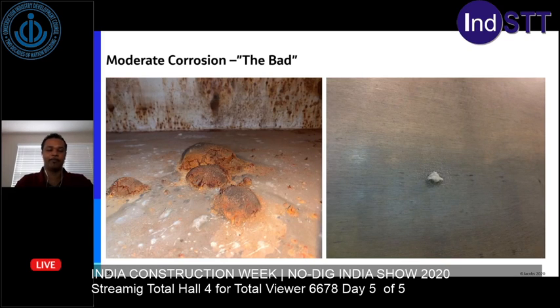And now we have a couple photos of moderate corrosion. This is considered the bad. The photo on the left has some corrosion nodules that have formed on the carbon steel tank floor. And you can also see that there are some pits starting to form on the shell of the same tank. Now on the right side, you will see a more exotic material with a feature that's similar to the nodules on the other side, but this feature has crystallized and it has allowed the product to be maintained within the structure. So that additional time that this feature allows gives you time to go in and consider adding a liner to this particular material application. Next slide.